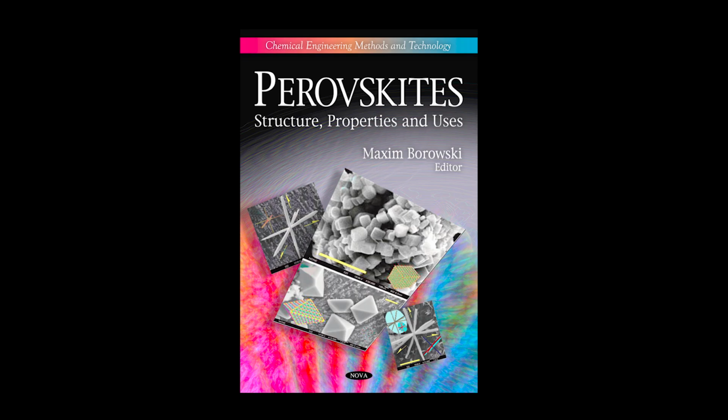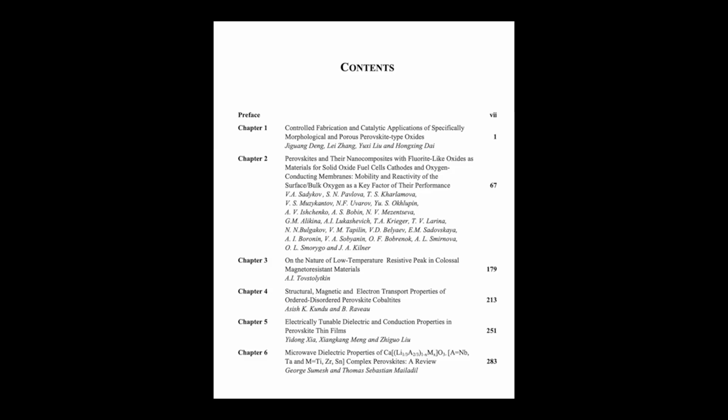Their value comes from two key properties. They have a very high intrinsic dielectric constant, epsilon, which means they can store a lot of charge in a small volume. And importantly, that dielectric constant is strongly dependent on an applied electric field. This property is known as tunability. High tunability means you can significantly change the material's capacitance just by applying a relatively small voltage. That's essential for creating high-density switchable memory elements.